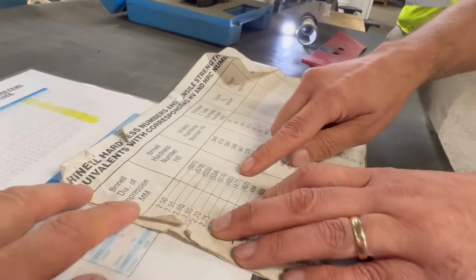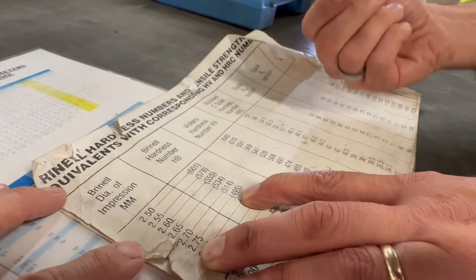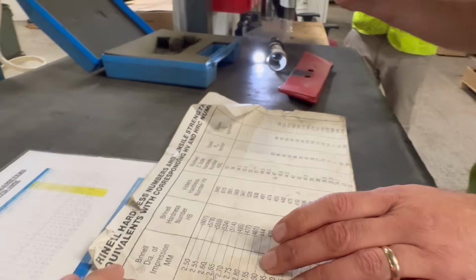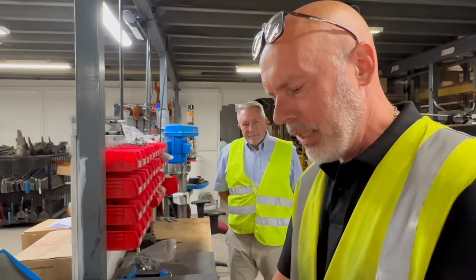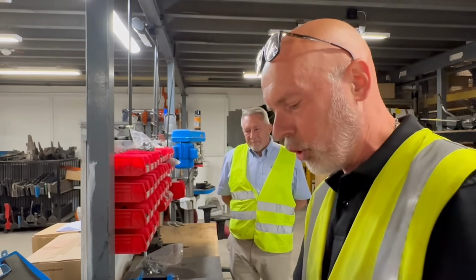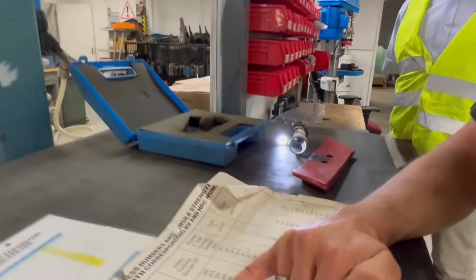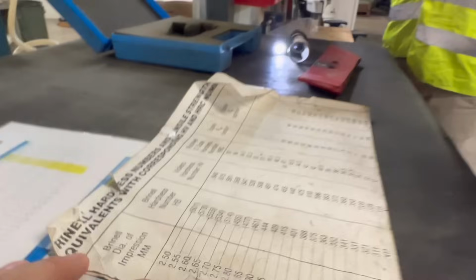On there, look, hardness Brinell figure 495. That's 495 hardness Brinell, and the spec for wearing metal is 444 to 514 hardness Brinell. Yeah. So that's sort of towards the top. So anything less than 444 would be deemed as not correct, obviously, and that would be too soft, which means it could wear out too quick. And anything above that, to 514 mark there, would mean it would be too hard, so it has a risk of snapping and that kind of thing.